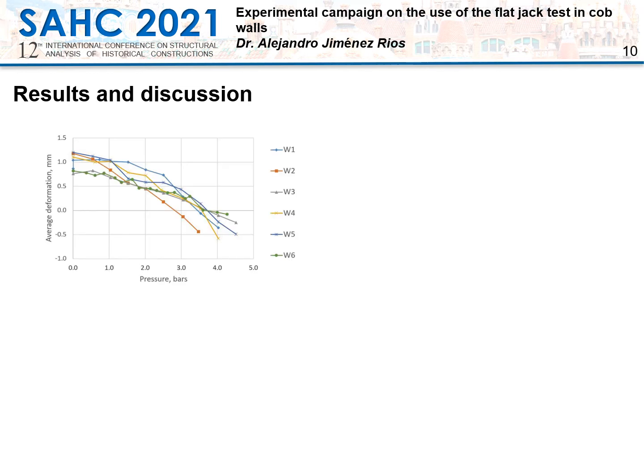In this figure, the average deformation recovery curves obtained from the single flat jack test performed in the 6 cob wallets are shown. It can be observed that as the pressure increased in the flat jack, the average deformation of the control points, originally caused by the release of stresses when the cut was made, decreased as expected. The recovery pressure of every wallet was computed as the linear interpolation between the 2 pressure points that presented the last positive and first negative average deformation value respectively. The mean recovery pressure was 0.345 megapascal with a standard deviation of 0.0327 megapascals.